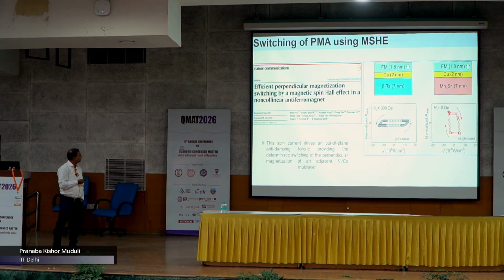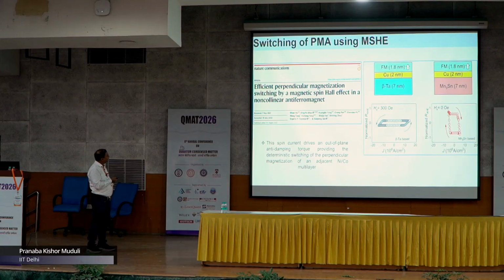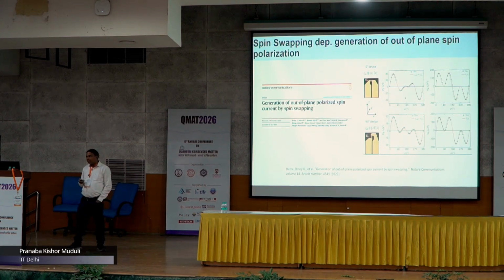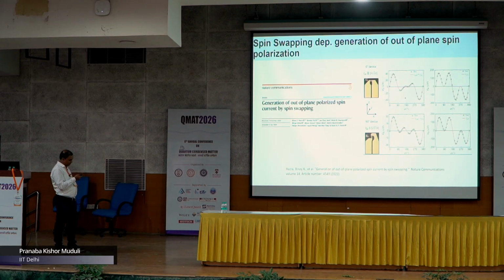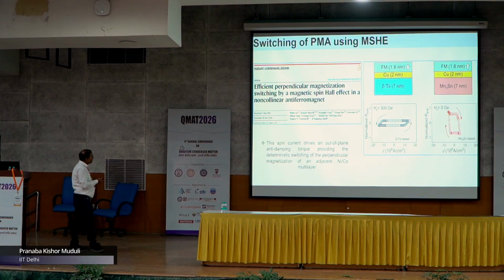So we wanted to check that, and we wanted to use that for switching. In this paper, they have shown that you can use that out of plane spin current in Mn3Sn to switch a very thin ferromagnet. It was cobalt nickel cobalt in this case. They are able to switch that using this magnetic spin-Hall effect, which they explained as due to the magnetic spin-Hall effect. However, there was a contradiction in the literature.